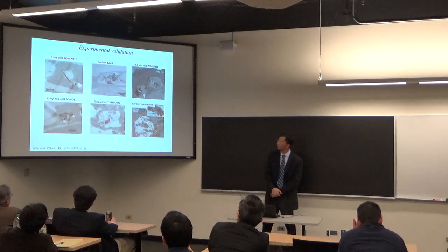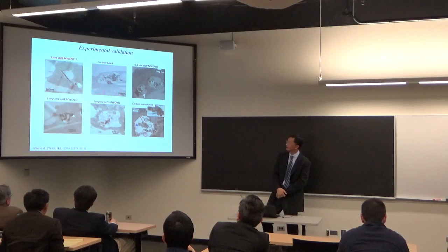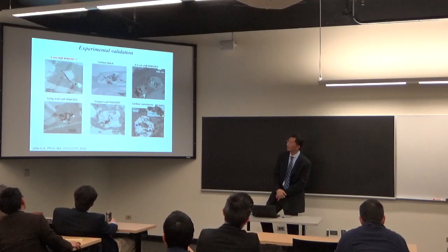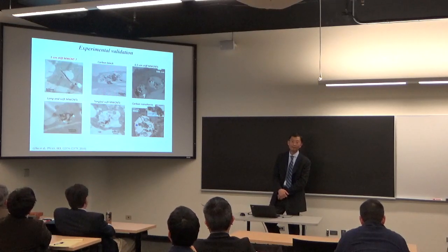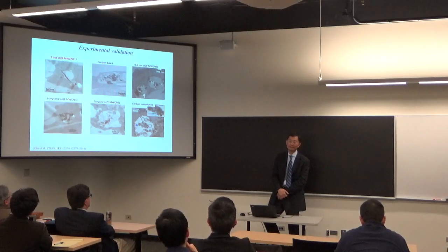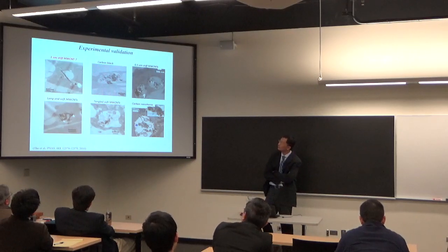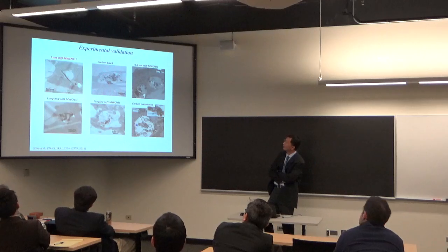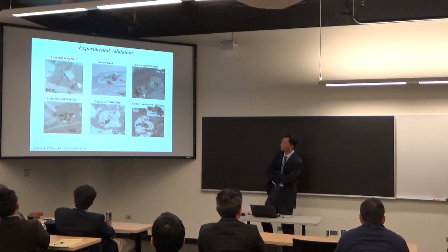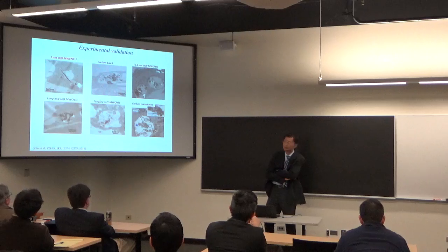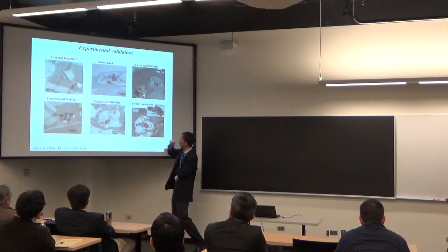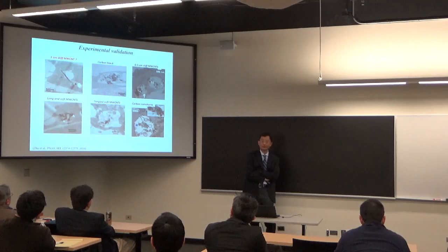So my collaborators and I have tested this concept. We culture cells with many different types of material. They all have the same chemistry, exactly the same chemistry, just to avoid controversy. So we tested carbon black, a one-micrometer-long stiff multiwall nanotube, a half-micron-long stiff multiwall nanotube, carbon black just like powder, long and soft carbon nanotubes, very long but like single-wall tubes, very soft and tangled, and carbon nanohorns, which have sharp edges, yet their dimension is small.